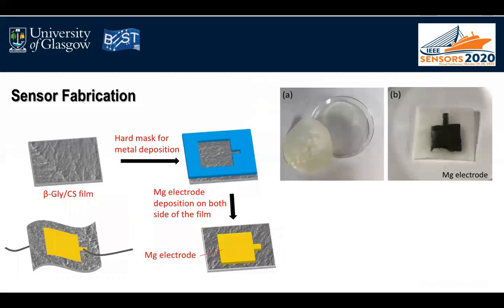After preparing film, a pair of parallel electrodes of magnesium were deposited on both sides of the film by thermal evaporation of magnesium and using a hard mask. As you can see in this figure, the magnesium electrodes were deposited on both sides of the film, and then it's connected to wire to be able to measure the signal.